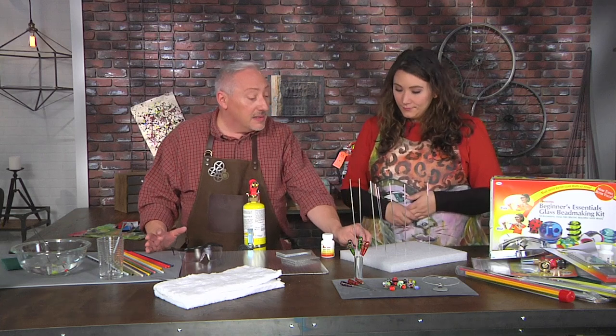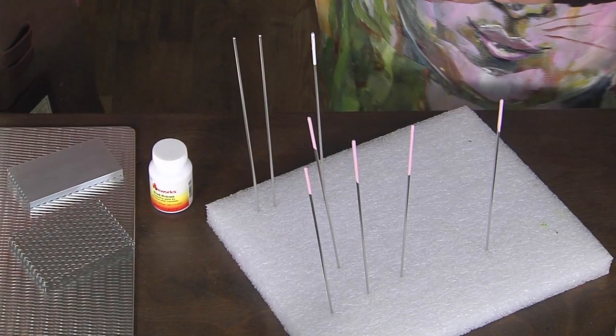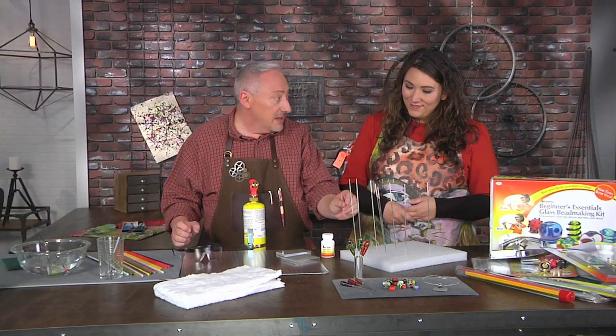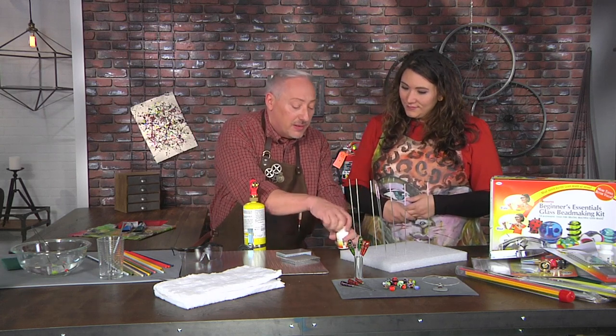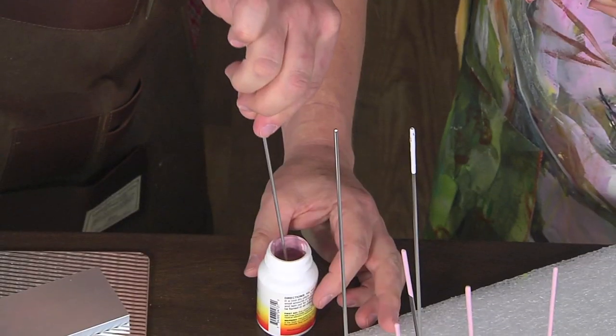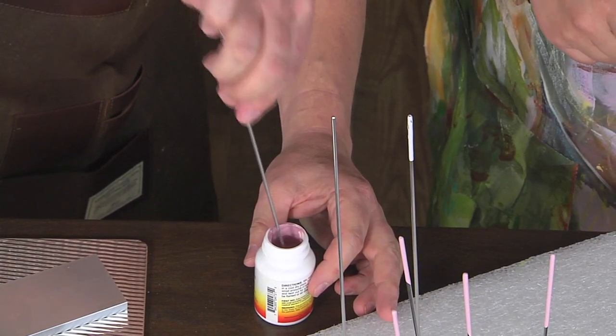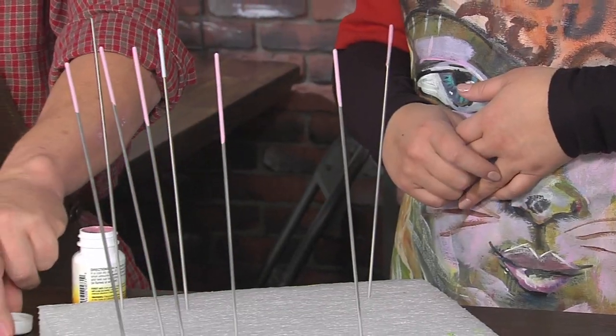We're going to start with these stainless steel rods called mandrels. We actually wrap the molten glass around them — that makes the hole for the center of the bead. But the glass would stick to the metal, so we have a bead release. To use it, you just take the mandrel, make sure it's well mixed — it should be the consistency of buttermilk — and stick it in. If you have a big glop at the end, shake that off.